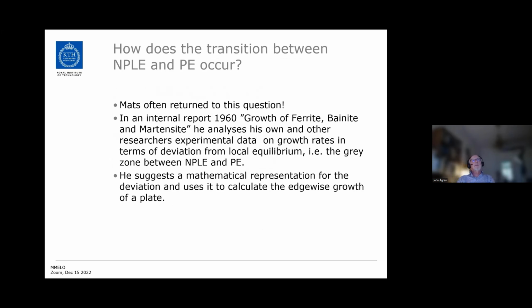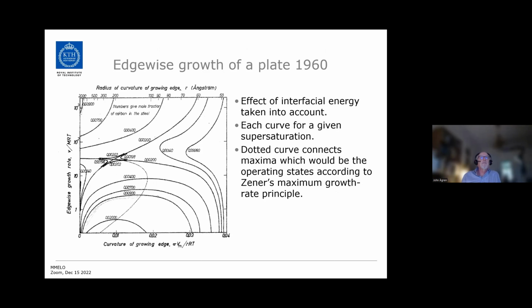So how does the transition between NPLE and para-equilibrium occur? This was something that Matz discussed many times. And in an internal report, 1960, growth of ferrite, bainite, and martensite, he analyzes his own experimental data and experimental data from other researchers. And he managed to evaluate the deviation from local equilibrium. That is in the gray zone between NPLE and para-equilibrium. And he suggests a mathematical representation for that deviation. And then he could use it to calculate the edgewise growth of a plate, for example, a ferrite plate.